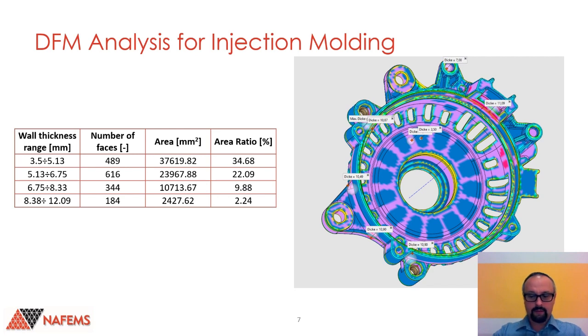But I think almost everybody knows that things aren't so easy here, and it is impossible just to take the old design, the old geometry, and use the new material, especially when it is a polymeric material, and just produce new parts. Because, as you can see here, the wall thicknesses in this particular part vary from 3.5 millimeters to almost 12 millimeters, which is, of course, mildly speaking, unsuitable for injection molding, and it will lead to huge warpage and make the part just not acceptable by anybody.